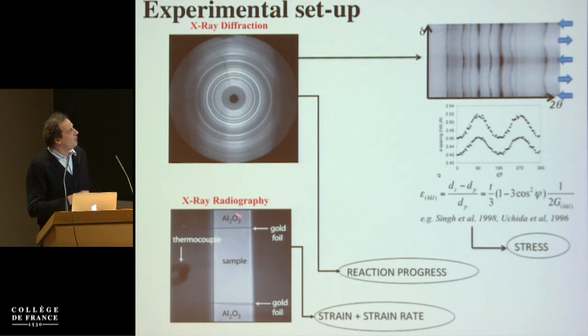So the first thing is that you use X-ray for radiography. So this is your sample. It's around 3 millimeters long and 2 millimeters in diameter. And we put two gold foils on top and on the other end that are strain markers, and we measure the distance between those two gold foils. And that way we have the strain and the strain rate if we take this image every 2 minutes.